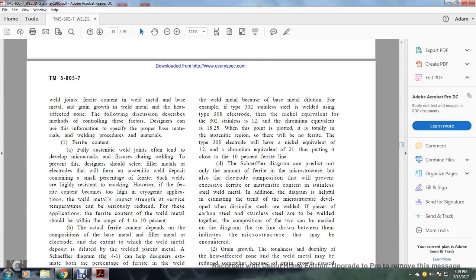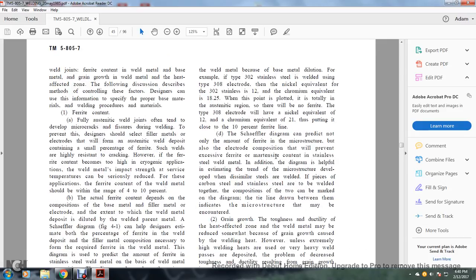For example, type 302 stainless steel is welded using a type 308 electrode. The nickel equivalent for the 302 stainless steel is 12. The chromium equivalent is 18.25. When the point is plotted, it falls in the totally austenitic region, so there is no ferrite. The type 308 electrode will have a nickel equivalent of 12 and a chromium equivalent of 21, thus putting it close to the 10% ferrite line.